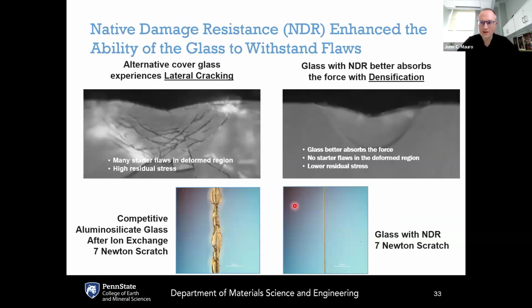I'm going to go ahead here and just mention that one last thing is what's called native damage resistance. This is something that we invented at Corning. This was commercialized as Corning Gorilla Glass 3 with native damage resistance, or NDR. And basically, this is another way to improve the practical strength of the glass by actually introducing a plastic deformation mode into the glass, where you can see this is an older glass under an indentation or under scratch compared to a newer glass under the same indentation or scratching conditions. And with this native damage resistance, this improves the resistance to cracking by about a factor of 3. So it's actually a pretty big deal that is used on a lot of smartphone covers right now.